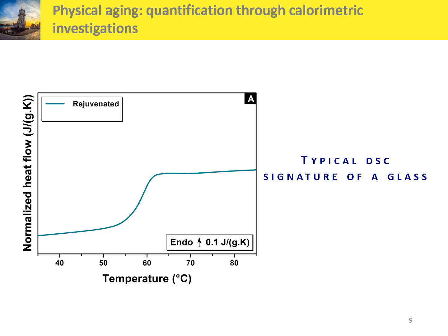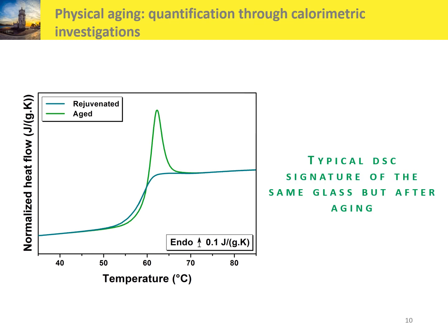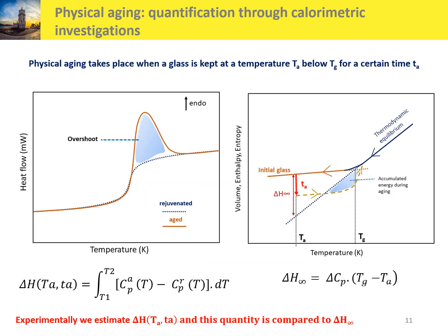The physical aging can be easily characterized by calorimetric investigations. This is the typical signature of a glass just formed or rejuvenated. And now, in green on these curves, we have the signature of the same glass, but after a certain aging duration. To quantify the enthalpy loss for a given aging duration, noted tA, we use this equation where CpA corresponds to the curve of an aged system and CpR to the rejuvenated system. And experimentally, we estimate the enthalpy loss, and this quantity is directly compared to delta H infinite.